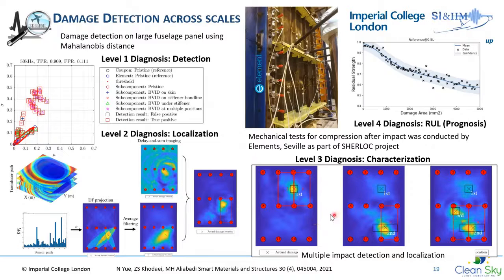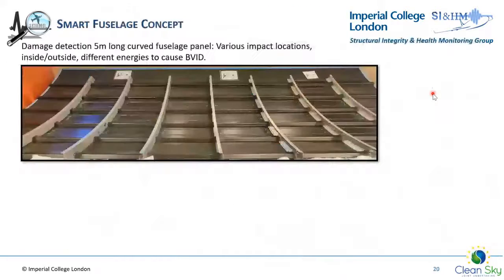Once you've detected your damage, then of course the next level is to do the residual remaining useful life analysis, which is the prognosis, and at the same time the residual strength, which you can see here. There's an actual test that has been done, but also we have to combine it with numerical simulation, where you include uncertainties in the material as well as load and so on. And you can then set your detectable damage threshold based on reduction in the ultimate load.